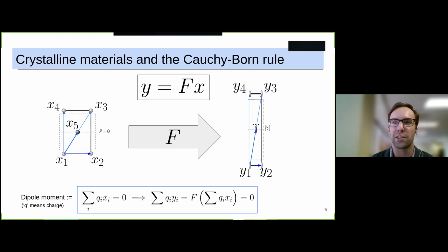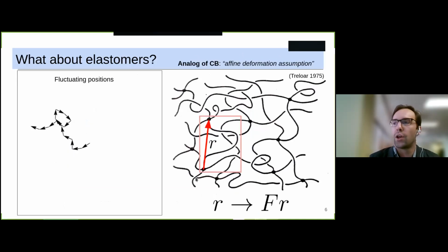And so this means that piezoelectricity is really something special. You need to break symmetry in some way, or your material needs to be violating the Cauchy-Born rule in some weird way. But it's pretty easy to fix this by allowing each of the lattice vectors to map under a slightly different deformation gradient. So if we have a strain gradient, if F is changing in space, then this can now give rise to a net dipole moment, a net polarization within the crystalline material. Okay, and so I think that's a nice clean picture of piezoelectricity and flexoelectricity in crystalline materials.